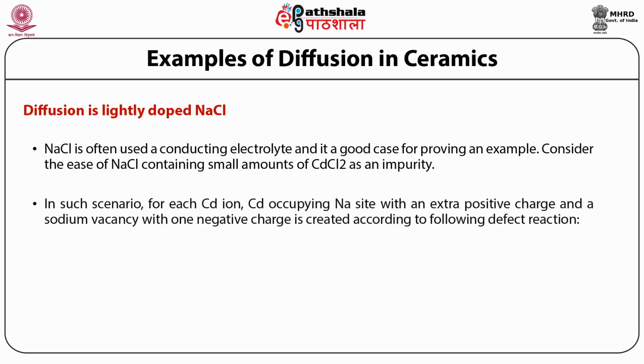In such a scenario, for each cadmium ion occupying a sodium site with an extra positive charge, a sodium vacancy with one negative charge is created according to the following defect reaction. So the first reaction is CdCl2 in the presence of NaCl gives Cd_Na dot plus 2Cl_Cl^x plus V_Na prime.